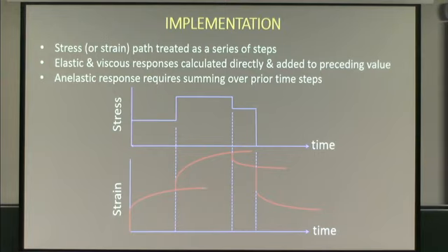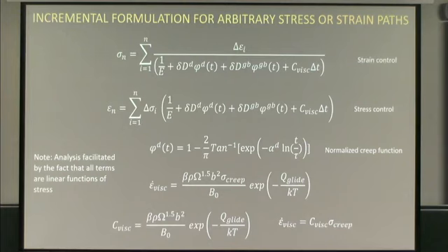You apply another step, you still have to keep track of this guy. That's where the hereditary integral comes into play. And then this new step creates a new little jump, and then it has its own relaxing function according to the model. If they drop, boom, same thing. So you can apply that method of calculation either in terms of an increment in strain, and you just divide that and sum up over all your time steps with the compliances here. In this case, elastic are two anelastic mechanisms, and then the viscous compliance for each step.